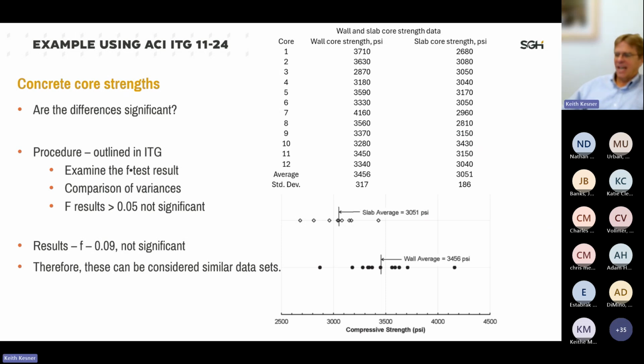So just for this data set, despite the differences in the standard deviation, that F test result indicated that the differences were not statistically significant. And what that allows you to do, that provides you a much bigger sample, now instead of having 12 cores in 2 different sets of samples, you can really consider that one statistical sample. And there are similar data sets. That helps you out in your analysis. Now you have a much bigger sample.